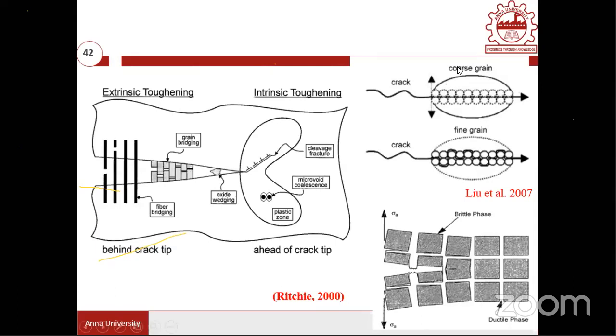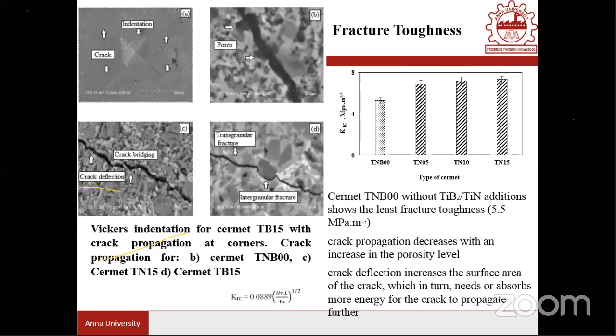And here an example is given. When you have a coarse grain, the path taken by the crack is very minimal. But when you have a fine grain distribution, the path taken by the crack propagation would be greater. That means a greater amount of energy is needed to propagate the crack to reach failure. So the energy requirement will be greater. And when the energy requirement is greater, the toughness value would be higher. So that is the case here.